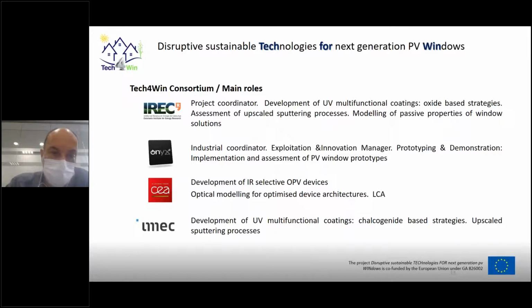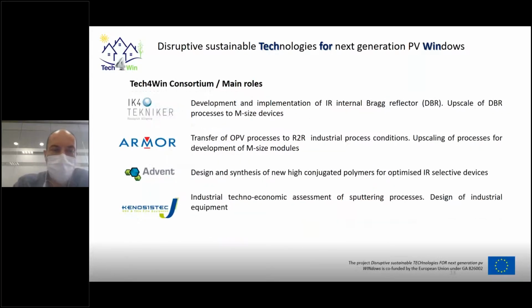We have also participation of CEA in France. They have a strong background in OPV technologies, OPV solar cells, and they are mainly in charge of the development of the infrared selective OPV devices, and also in the optical modeling for the optimization of the device architectures. IMEC is also involved in the consortium, complementing the strong collaboration with IREC in the development of the ultraviolet multifunctional coatings. IREC is working essentially on oxide-based strategies. IMEC are working essentially on chalcogenide-based strategies, and they will be also in charge of the scaling of the sputtering processes. We have also the participation of IK4-Tekniker, Technology Center in the Basque Country in Spain, which are in charge of the development and implementation of the internal Bragg reflectors for boosting the efficiency of the infrared device.